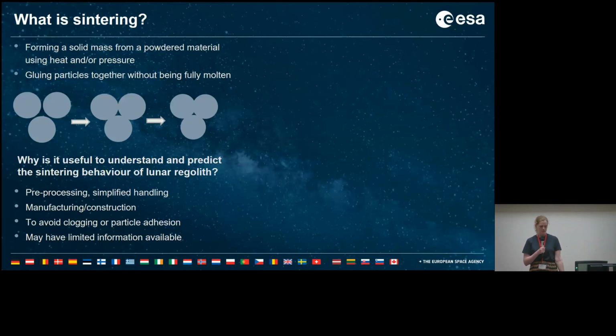So briefly, what is sintering? We're forming a solid mass from a powdered material. We're gluing the particles together without them being fully molten, so just a kind of edge-to-edge contact. And why is it useful to understand and predict the sintering behavior? We might use sintering for pre-processing, for simplified sample handling, like in this case. Sintering is also used widely in manufacturing and construction. And we might just want to avoid sintering altogether, like avoid clogging something like a fluidized bed reactor or some kind of transport system. And in general, we might have limited information available, so we might not know the melting behavior of the material that we're working with, but we might have information like the composition.